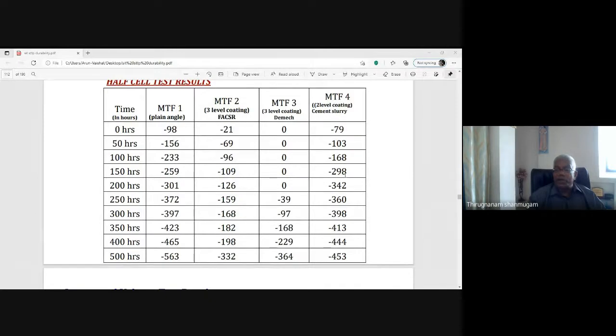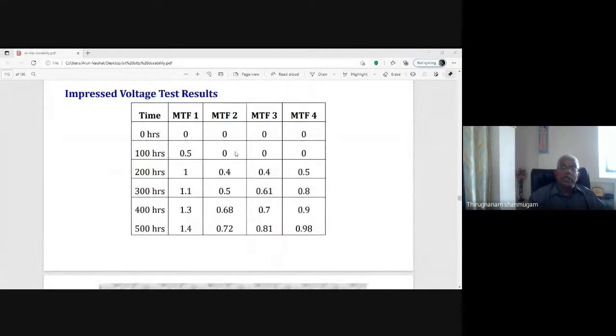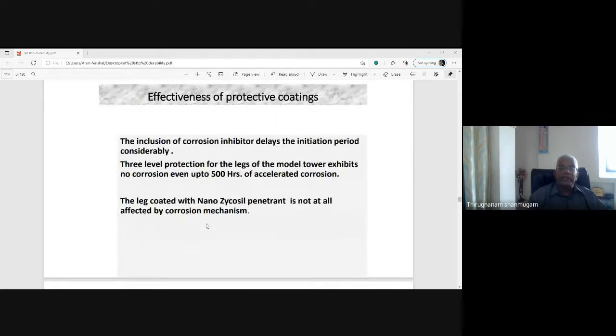The cement slurry coating is slightly less performing, and it crosses this limit by 250 hours. Slightly better, but inferior to the 2-level coating or 3-level coating, etc. The impressed voltage performance is also the same. The coatings with 2-level or 3-level are better as compared to uncoated angles. Effectiveness of protection: the inclusion of corrosion inhibitor delays the initiation period considerably. 3-level protection for the legs of the model tower exhibits no corrosion even up to 500 hours of accelerated corrosion. The leg coated with Nano Zycosil penetrant is not at all affected by the corrosion mechanism.